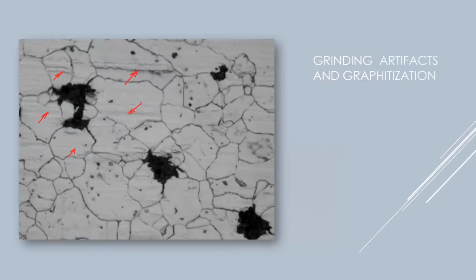This one is taken at high temperature. In fired heaters, if they're carbon steel, they're susceptible to graphitization. Graphitization just means that the pearlite is being converted into graphite, because that's the stable phase. You can have a lot of graphitization in your pipe before it's a problem. But what sometimes happens is that it concentrates close to the heat affected zone of a weld. And now that's bad. So if you're a client and you find graphitization, you probably want to look at your welds. Unfortunately, you probably won't see it with an in-situ replica at the weld, but you can see it here.